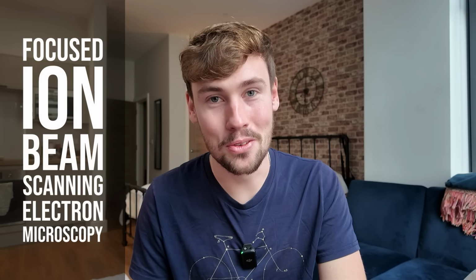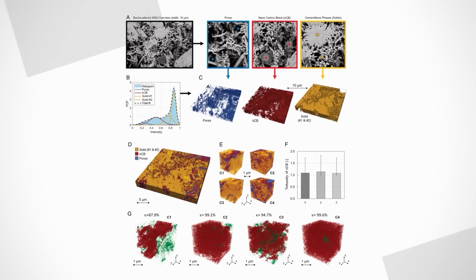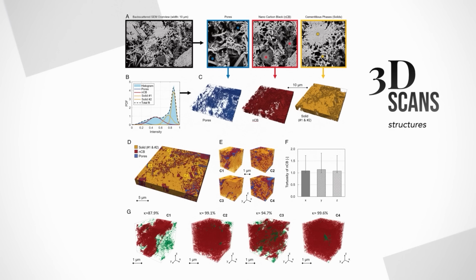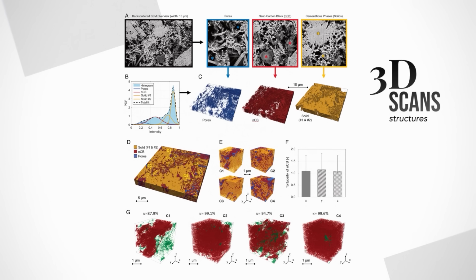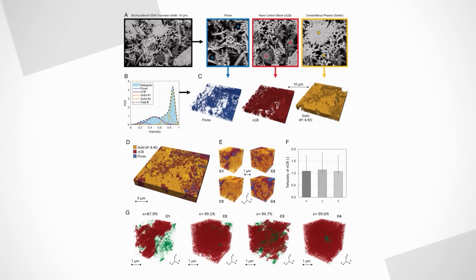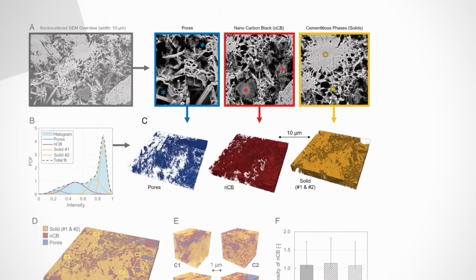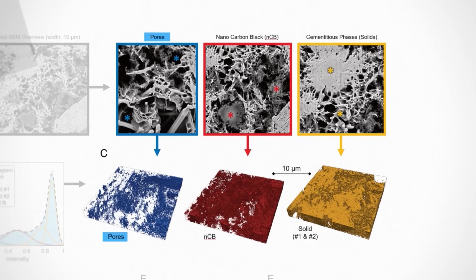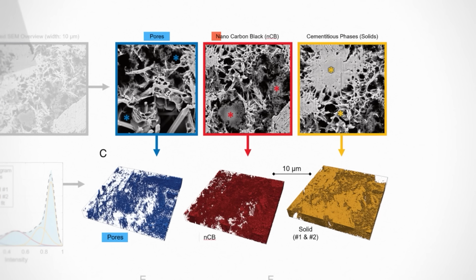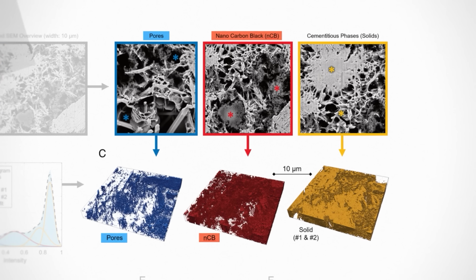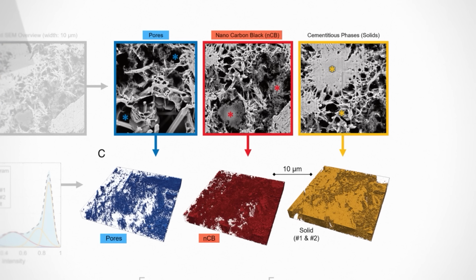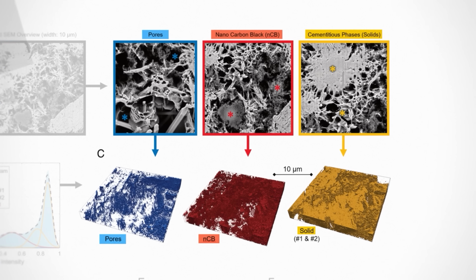Now that is a difficult phrase to say. With this method, they were able to create 3D scans of the structures inside their cement paste, and these pictures show the results. You can see 3 different networks. One is for the pores where the liquid electrolyte goes. One is for the carbon that makes up the nanostructure that is the electrodes, and the last one is for the solid cement. With all of these fit together, you end up with the electrolyte, the carbon electrode, and the solid cement that causes the structural stability.